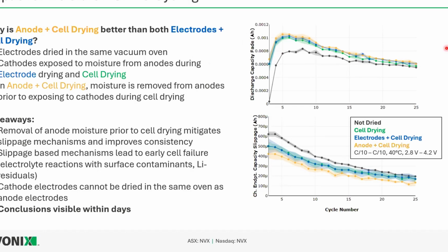For number one, higher C rate cycling. So it really depends on what the goal of the testing is. So in these cases, like this moisture study that I'm looking at, we're trying to find really tiny differences in the electrochemical reactivity between the electrodes and the electrolyte. So we're not really concerned so much with kinetic effects within the cell. We have other ways of probing kinetics like EIS or DCIR that are all really great methods for that.